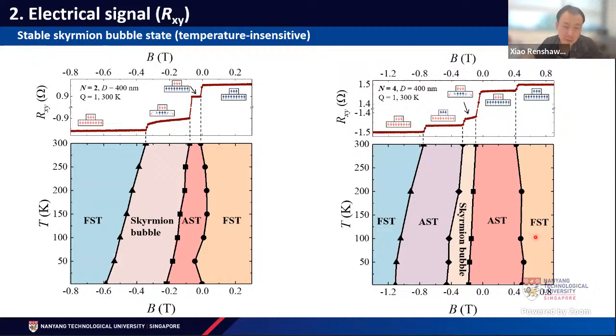We also, of course, summarized what we have already measured into a phase diagram. So on the vertical axis is the temperature, horizontal axis is the magnetic field. From this phase diagram, we can immediately identify the range, the window where we can get skyrmion-like magnetic states or skyrmion bubbles. And this helps us to navigate through the phase easily.